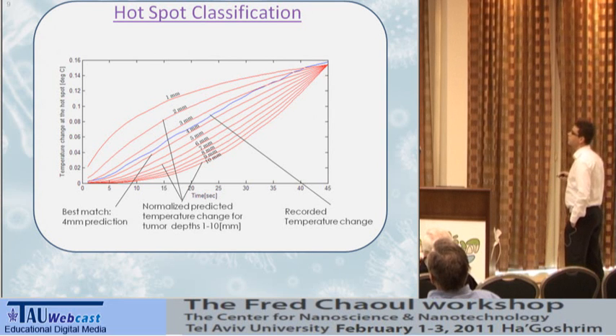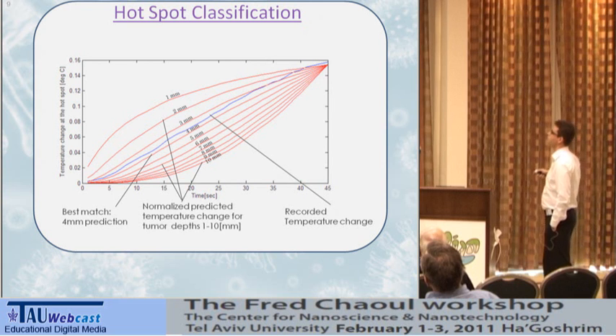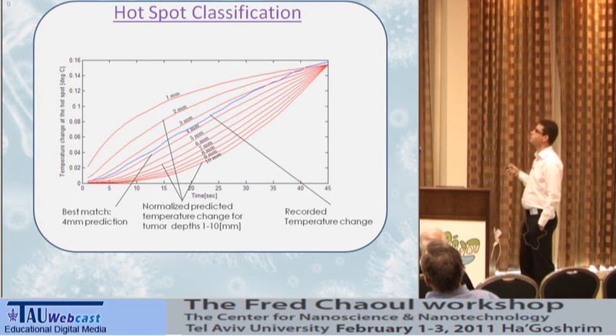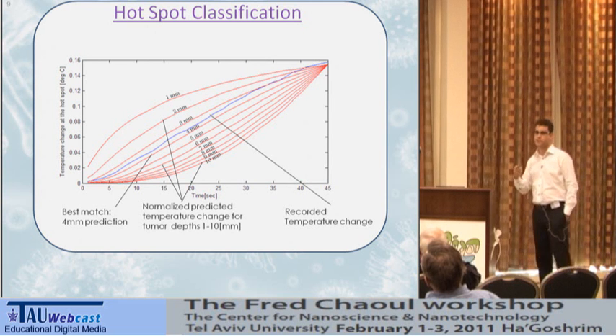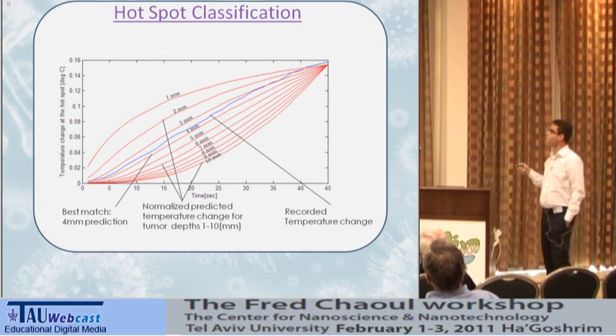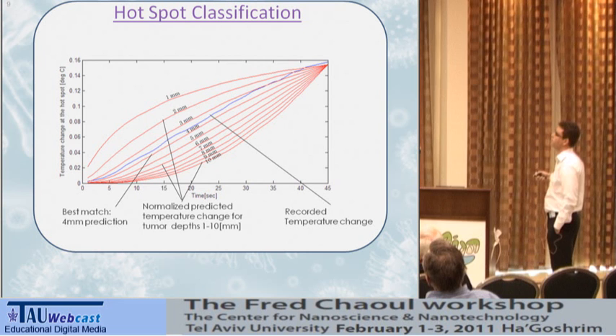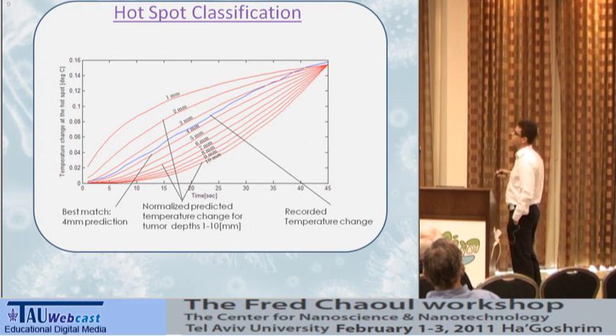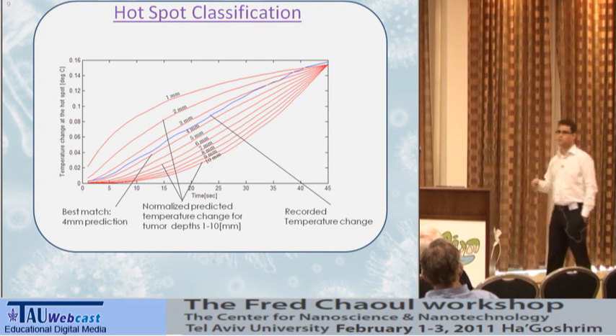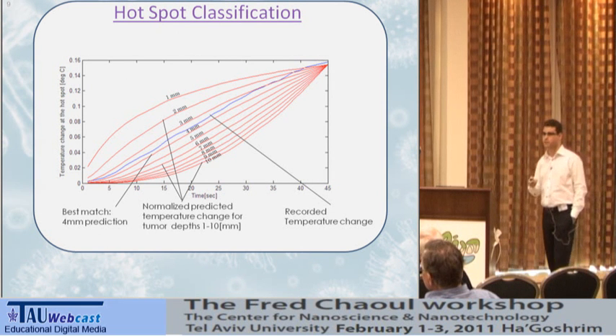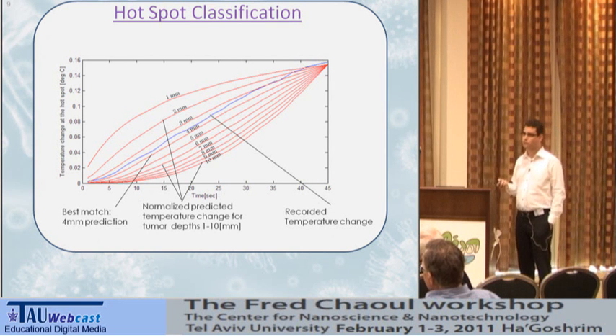and the blue curve is what we get from one of our measurements, and we compared it to the simulation result we have. So you see, this is simulation result for 1 millimeter deep tumor, 2 millimeter deep tumor, 3 millimeter, and so on and so on. And as you can see, it fits quite well to 4, maybe 3.5 millimeter deep tumor.